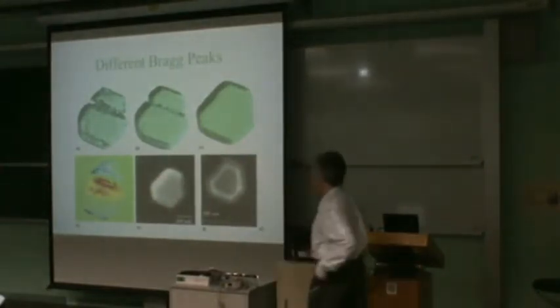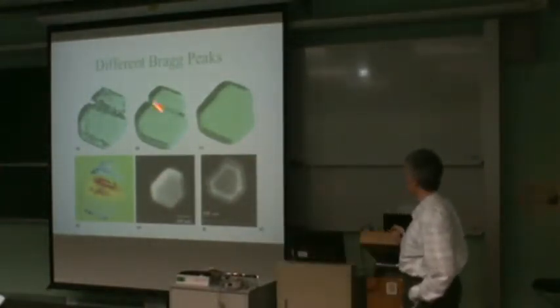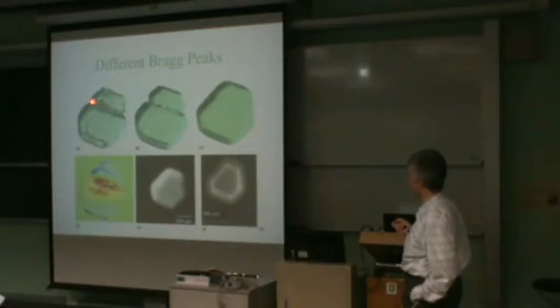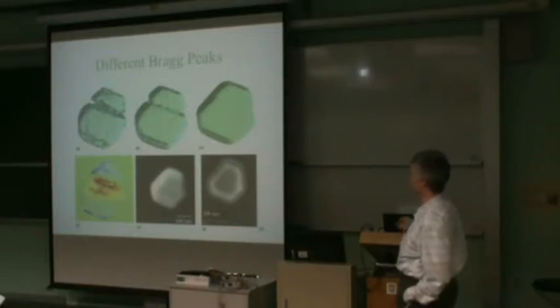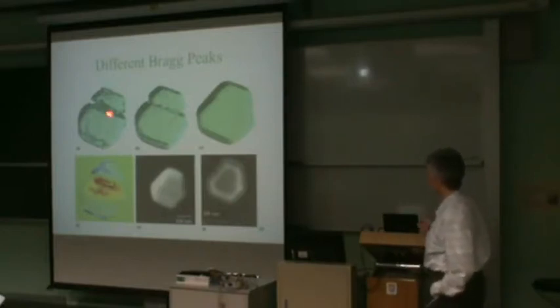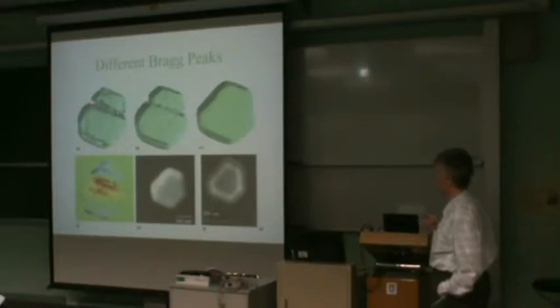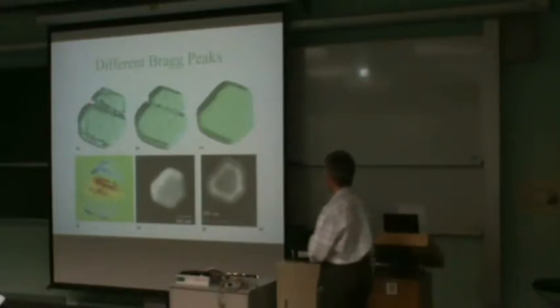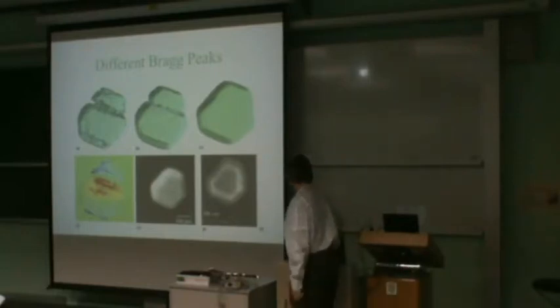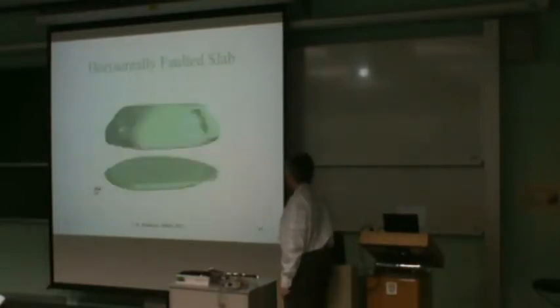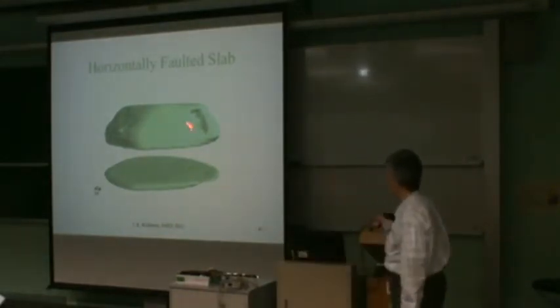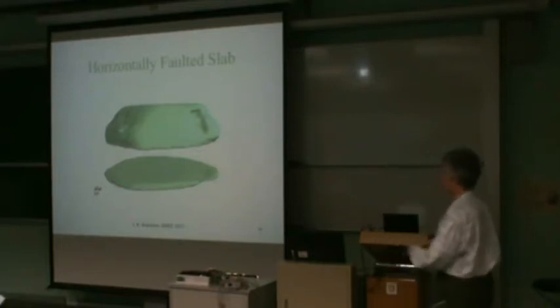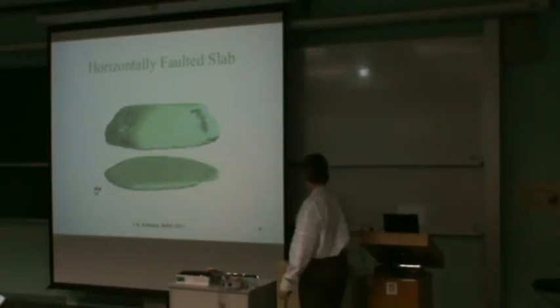And these are the kind of images that are coming out. We see quite often these planar defects where we're seeing missing pieces of crystal where the missing piece is reversed in its stacking sequence and so has its Bragg peak at a different location. And if we go to that other location, we can insert the missing piece of the crystal. So we're seeing stacking faults quite nicely in these gold crystals. Here is a pair of stacking faults that completely isolates the top and the bottom of the crystal, and there's a big slab of missing crystal which is rotated 60 degrees away.